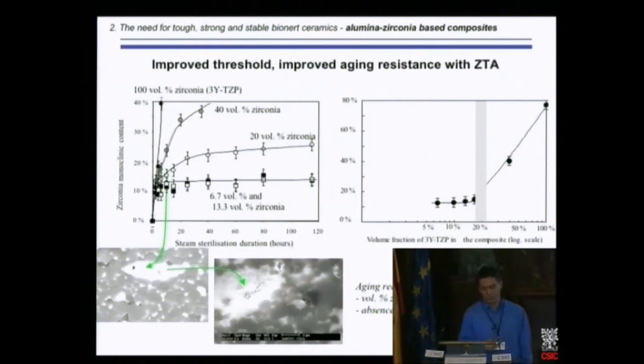When you have an alumina matrix and isolated zirconia grains, you have almost no problem with aging. So this is, for example, the amount of monoclinic content we measured after a certain time of aging versus the volume fraction of zirconia in the composite. It ranges from 5% zirconia in an alumina matrix towards more than 50% zirconia in the alumina matrix, and this is zirconia alone. What you find is that the lower the zirconia content, the larger the stability of the material. That's quite obvious. But what is important is that below the percolation threshold, in terms of volume fraction of zirconia, so below, let's say, 16% of zirconia, there is almost no aging at all. So you can process a tough and strong ceramic based on the tetragonal to monoclinic transformation of zirconia during crack propagation, but which is highly aging resistant.